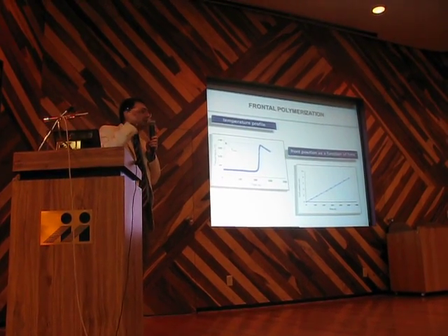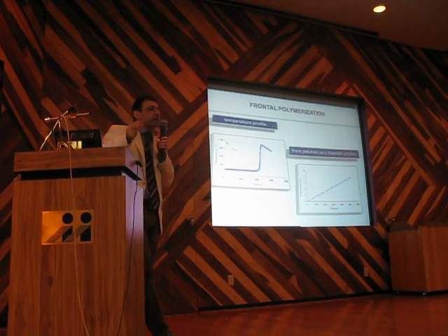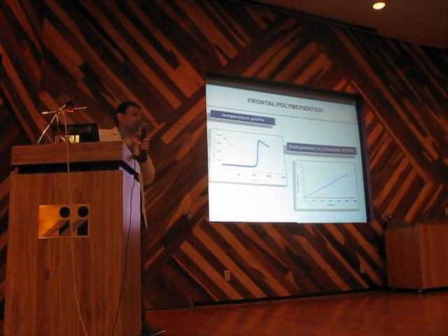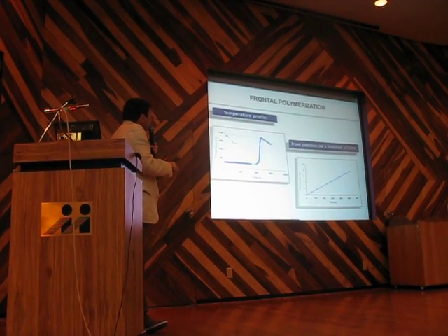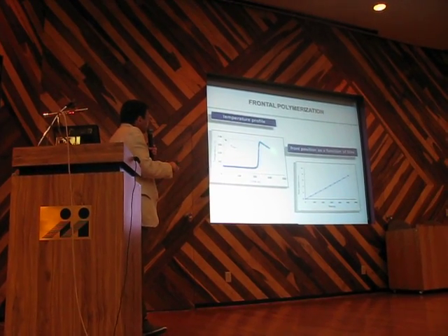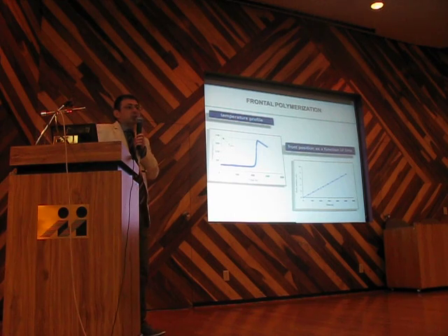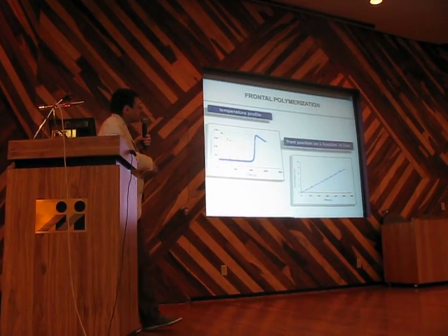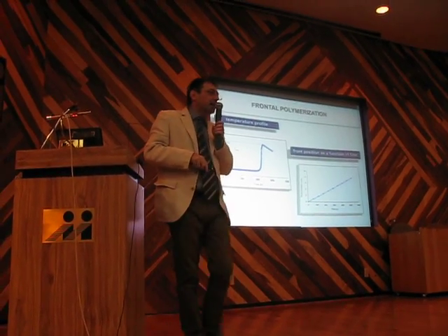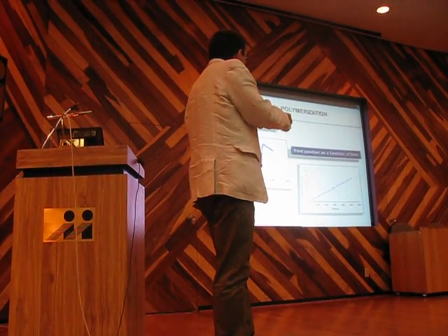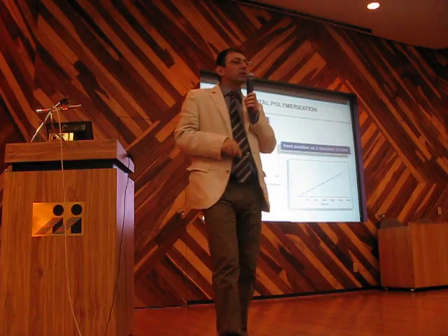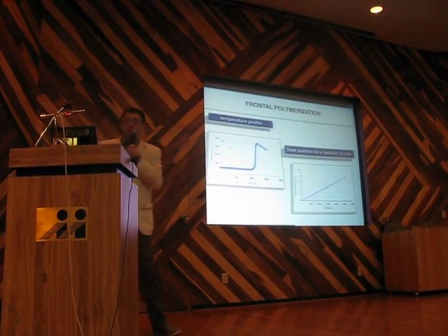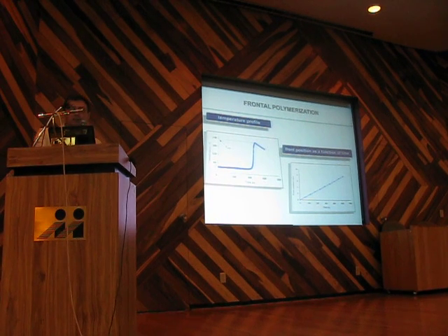It means that it's the only phenomenon occurring in our reactor at a given time. Then we have an increase of temperature, and then the system cools. If we measure the position of the front as a function of time, we discover that fronts move at a constant velocity.